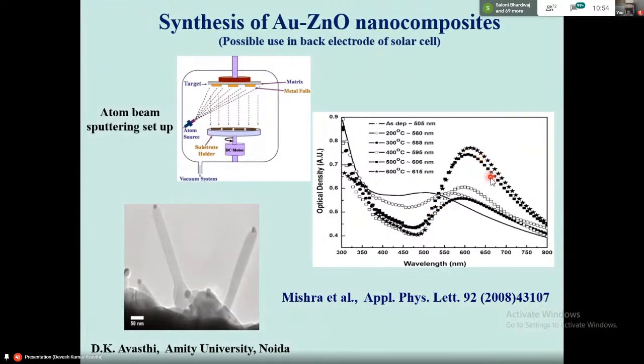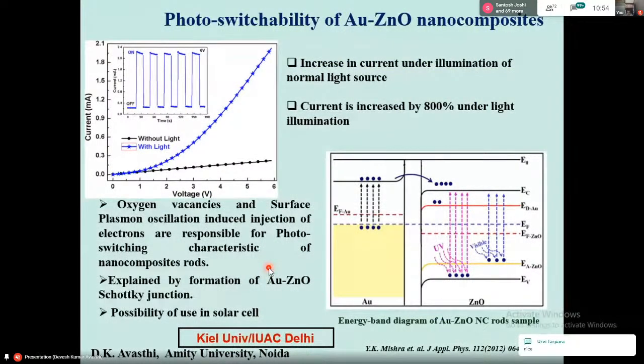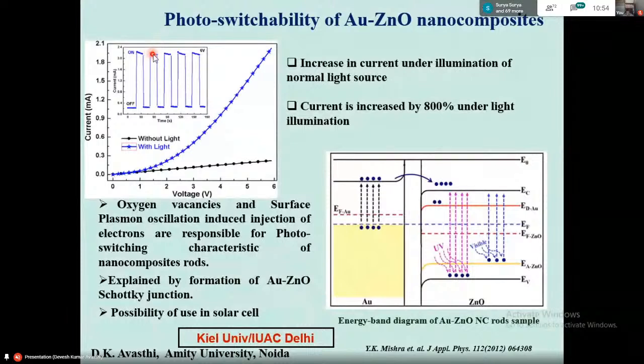And this is the SPR, surface plasmon resonance, visible by UV-visible spectroscopy, which shows a plasmonic response. This showed very interesting photo switchability. That means for this particular material, we apply voltage to it, and then when we put light on it, the current increases. When you switch off the light, it comes back. When you put light again, it goes up and remains almost constant. And this can be repeated many times. So this material is able to supply electrons in the system in the presence of light. So this material becomes interesting as a back electrode in solar cells and other devices where you need a supply of electrons in the presence of light.